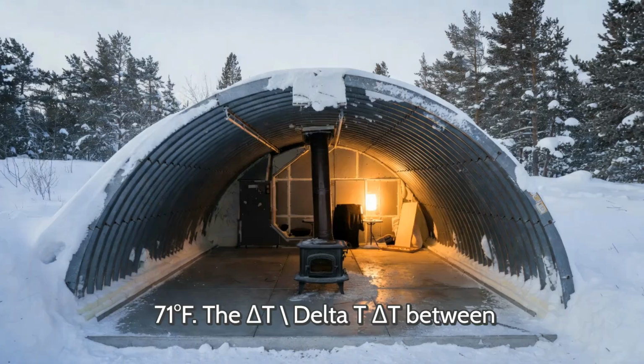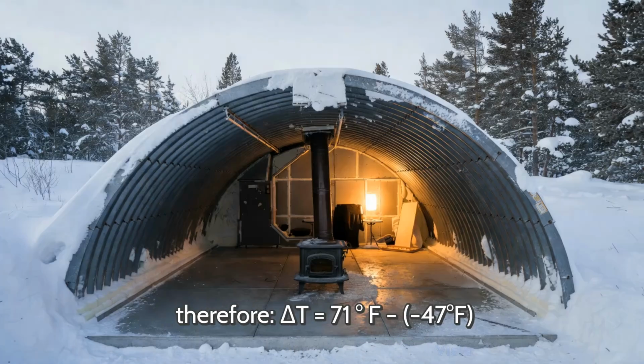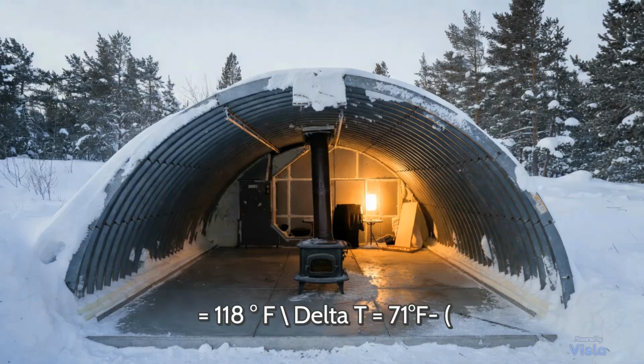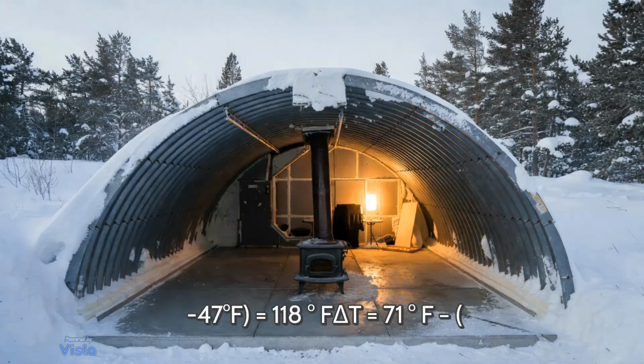The delta T between interior and exterior was therefore delta T equals 71 degrees Fahrenheit minus negative 47 degrees Fahrenheit equals 118 degrees Fahrenheit.